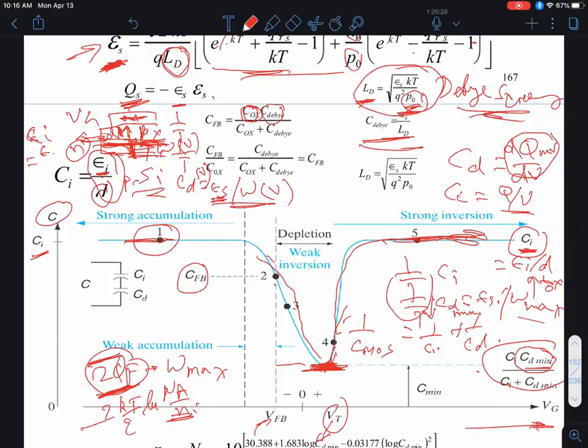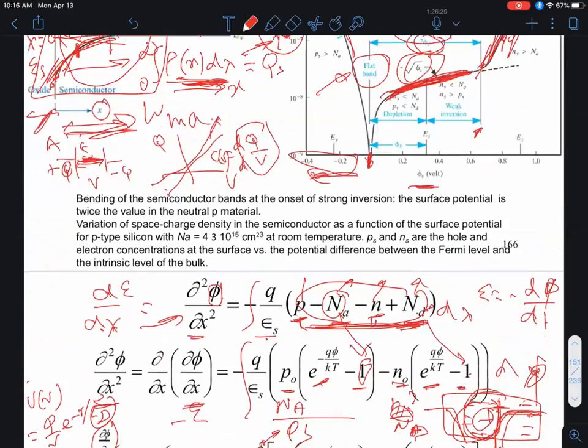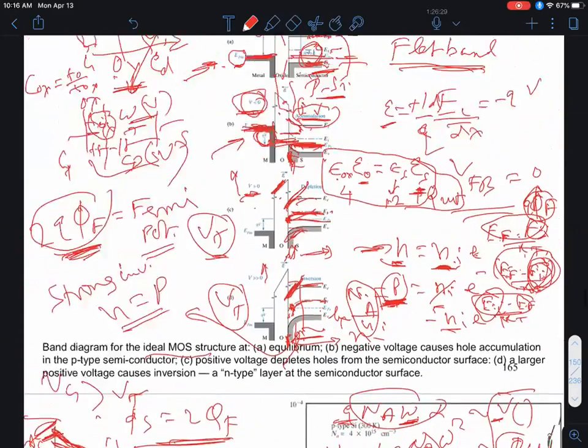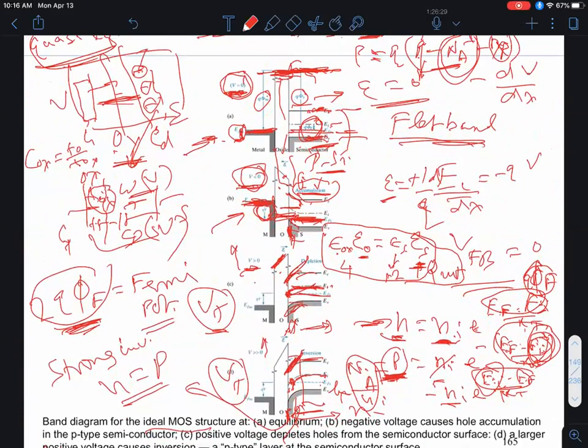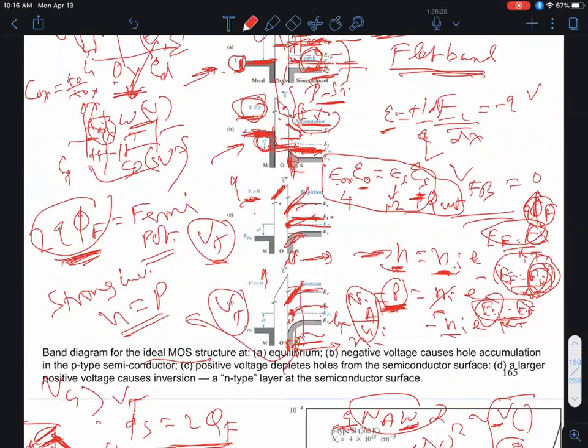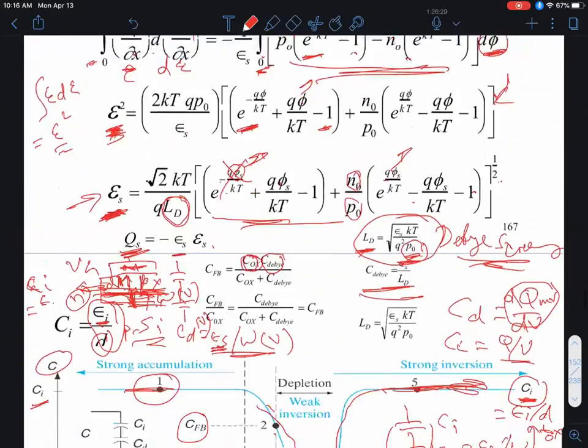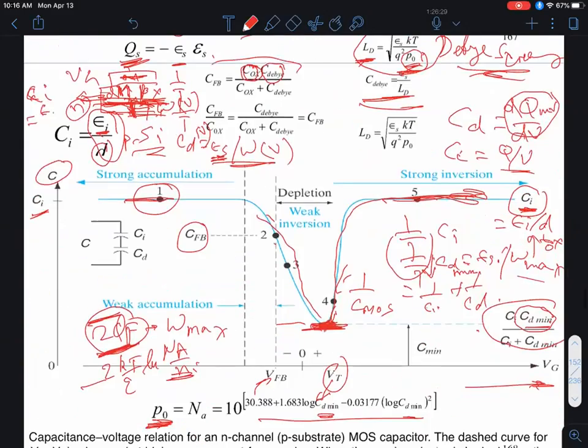So it turns out under flat band conditions, when you change the gate voltage a little bit, the bands bend around flat band a little bit, that gives rise to a so-called Debye capacitance over here in series with oxide capacitance, which is what I'm showing over here. So knowing what the doping is, you can calculate the Debye length, you get the Debye capacitance, from which you can get the flat band capacitance, which you can then read off from this, and that then lets you read off what the flat band voltage is.